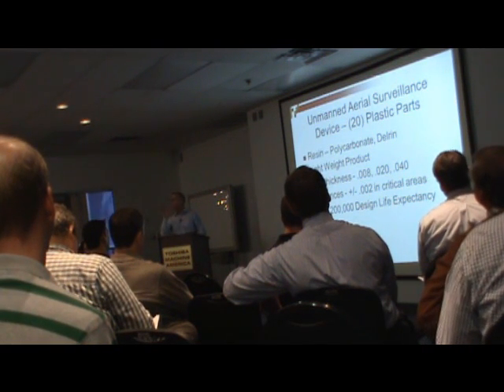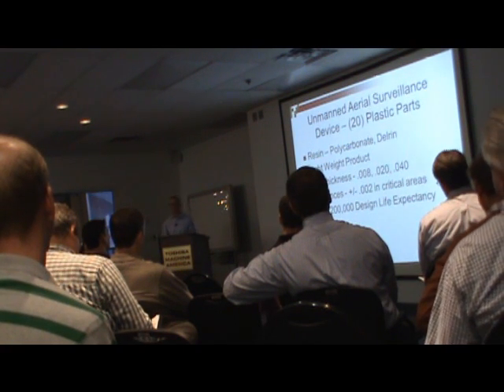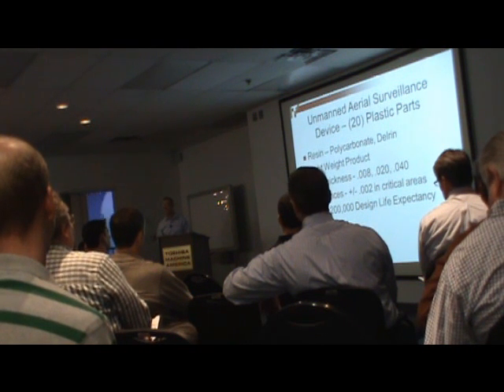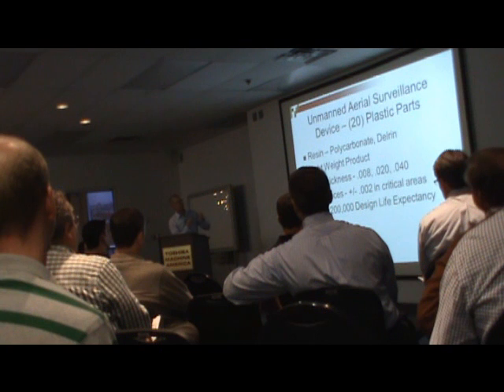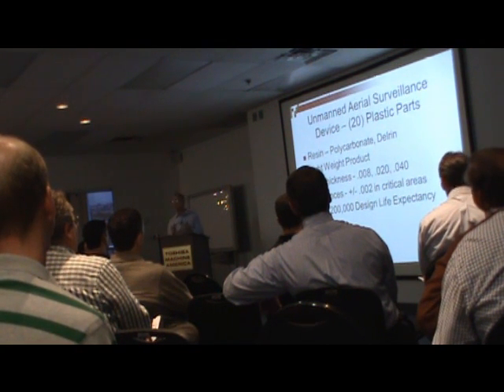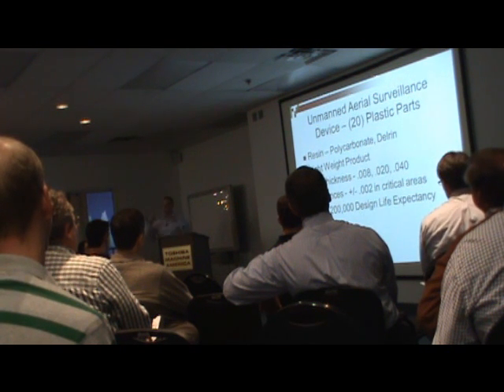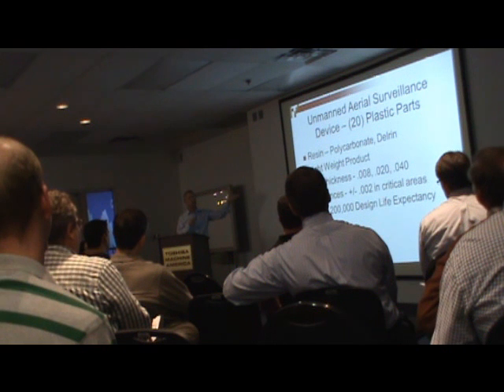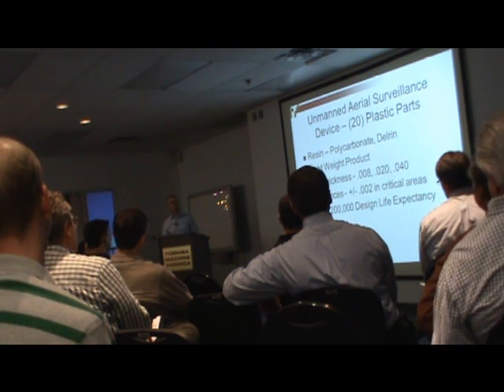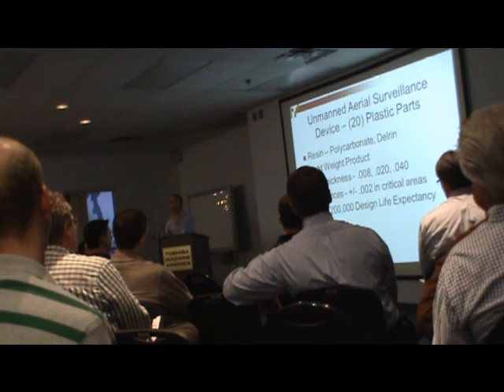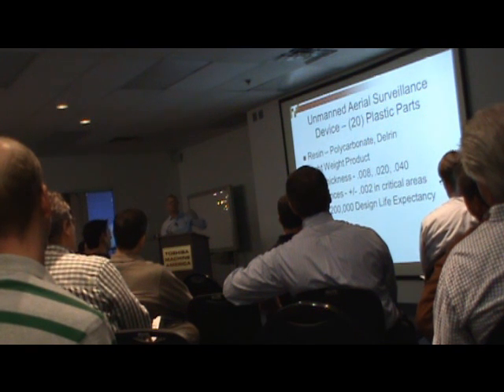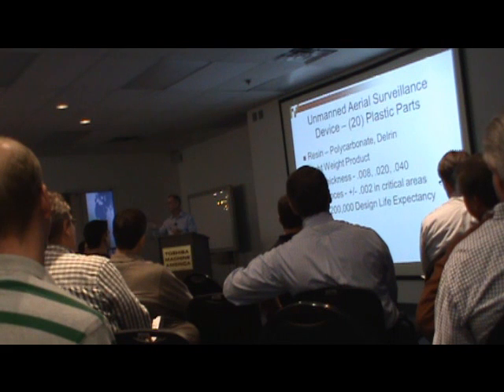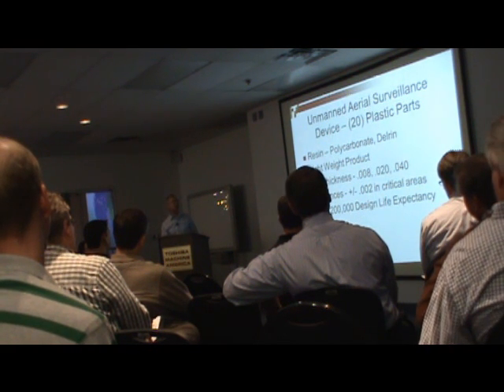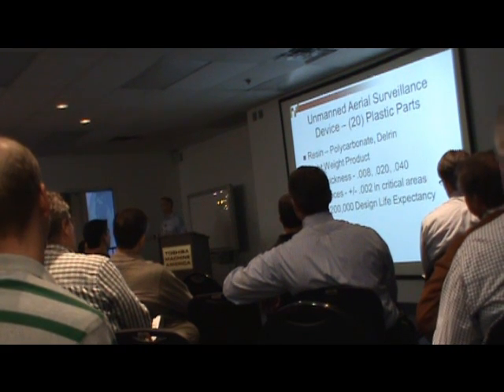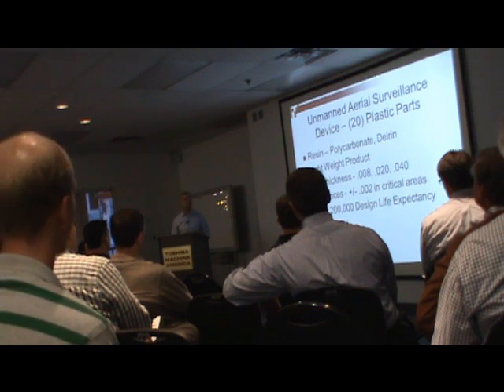This project is back there on the very right-hand display unit. There are 20 different components here, and the reason I brought the parts is this aerial surveillance device, it's unmanned, it's a little bit more than 3 pounds, and that's including the camera and everything. And it has to fly under certain variations that I don't know about. It's a polycarbonate Delrin part, 20 different components. The critical part for us was not the geometry, it was the wall thickness. Most generally, they're around 40 thousandths. It won't get any larger than 40, but it gets as low as 8 thousandths, and 20 in other areas, with tight tolerances of plus or minus 2. We signed up for this, and we're going to achieve over 200,000 design life expectancy.